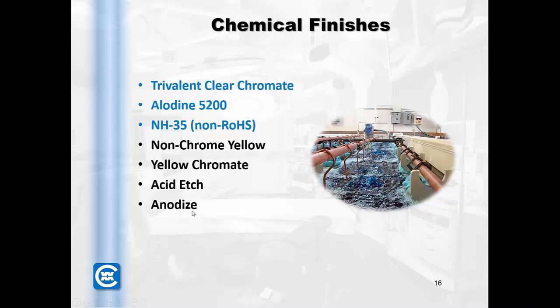Anodize, people hear that a lot, and that certainly can be done on die casting. We do it a lot for current applications. Just one thing to consider is anodize is typically not what we would consider a cosmetic appearance. On other types of processes like a CNC machined part, if you anodized an aluminum part that had been machined, that would give you a very nice cosmetic finish. On a die casting, the anodize just does not come out quite that well, and it's a little blotchy and not as even a finish as you might expect. So anodize is a fantastic pretreatment, and some people are able to use it as is without a top coat. Just know that it's not really being considered a cosmetic finish.